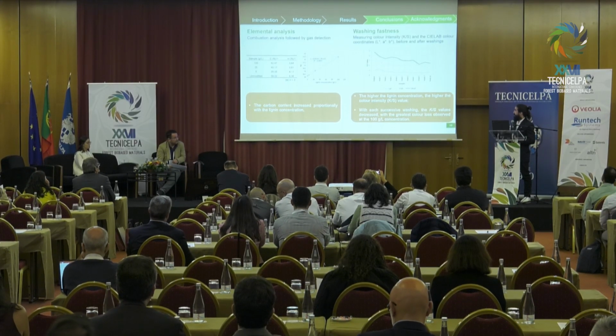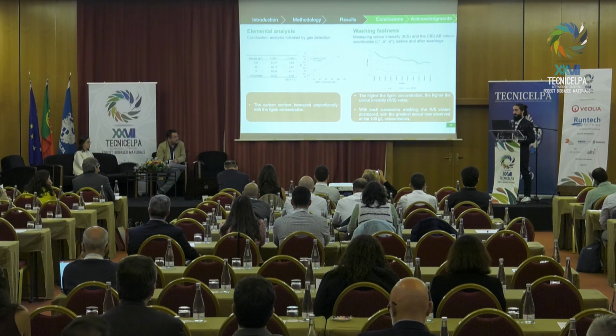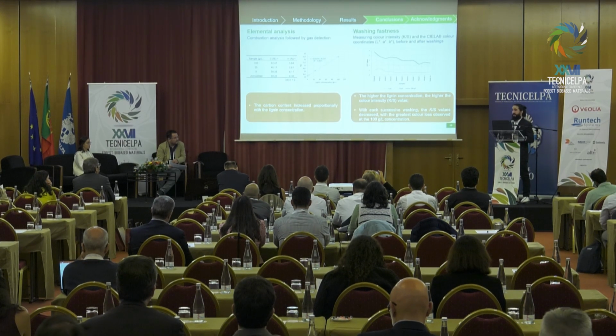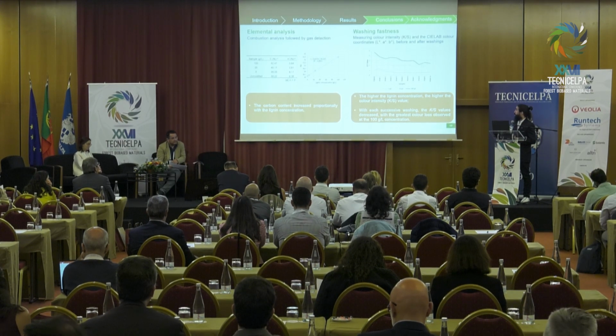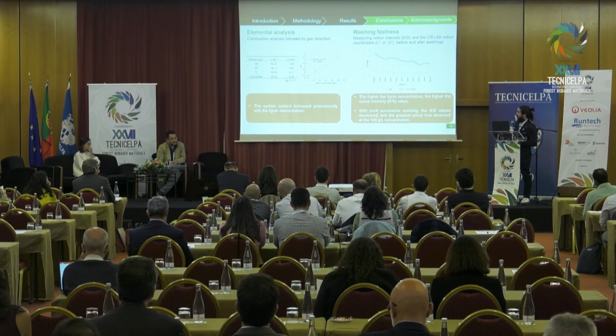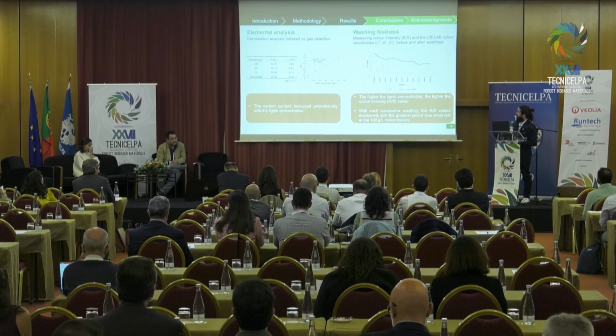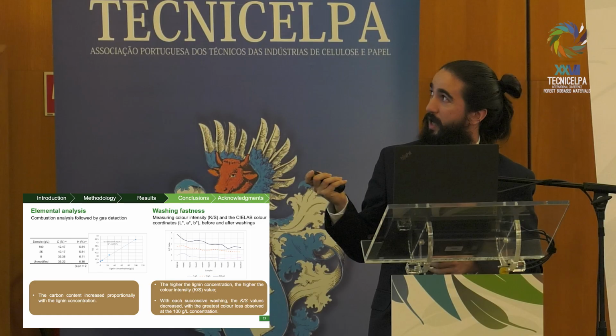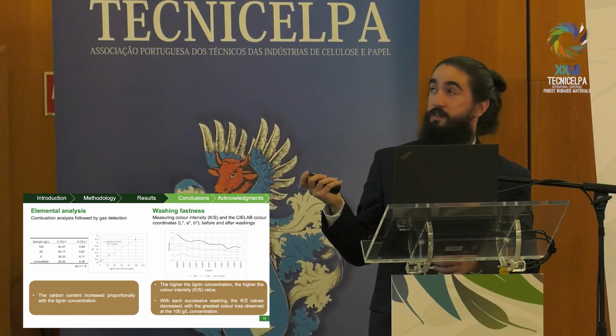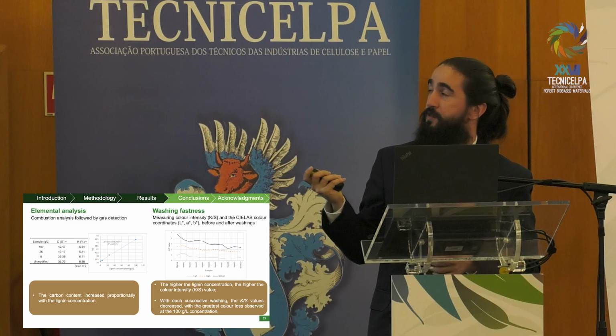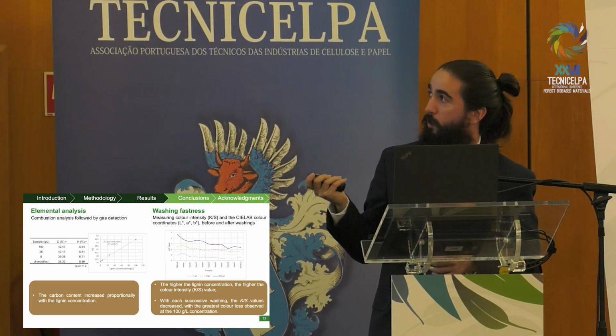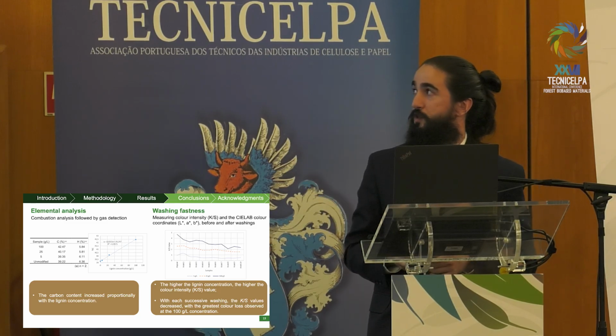Then the test of washing, successive washings. In this case, we measure the color intensity values and also the CIELab color coordinates, although we do not present them here. And as you can see, the more lignin we add, the higher the K/S value. But we can see for the highest concentration, a sharp decrease in the color intensity, an intermediate decrease in the intermediate one, and thus a low decrease in the lowest concentration.